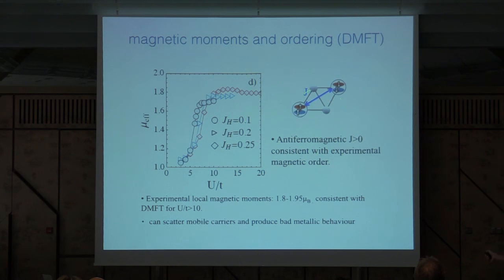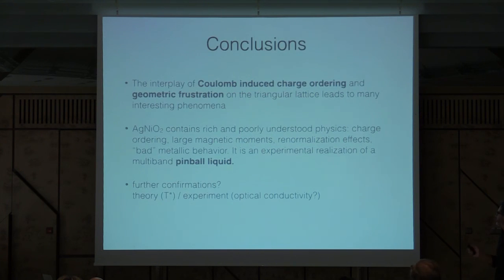We also did some calculations showing that there is an antiferromagnetic coupling between these local moments, and this explains why they order at low temperature. To conclude, I hope I showed you that when you combine Coulomb interactions and frustration, you can get a lot of very interesting physics. One example is this silver-nickel oxide that contains all these ingredients and shows many poorly understood phenomena, and we think it's a neat experimental realization of this multiband pinball liquid.